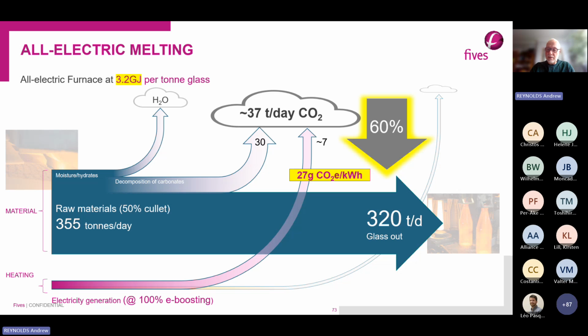Of course, in France in particular, this is helped by the fact that the scope 2 emissions are very low, because in France, the CO2 cost of each kilowatt hour of electrical energy is low. In fact, I think at the time of this project, we were calculating on about 27 grams of CO2 per kilowatt hour of power. You compare that with an average in Europe of about 250 to 300 grams per kilowatt hour. So you can see in France, it's particularly attractive.